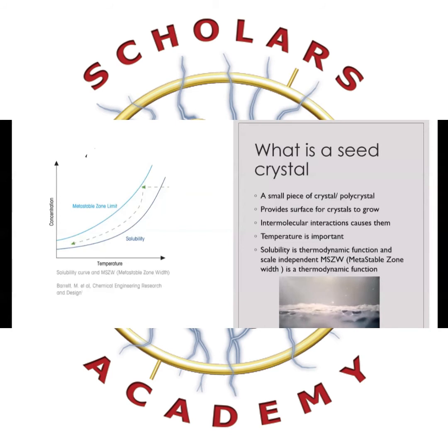Now, if you take a look here on the left-hand side, I have a solubility curve and an MSZW, metastable zone width, which I'm going to explain. Having decided that a process should be seeded, the next step is to identify at what temperature or what point the seed should be added. This is where the solubility or the MSZW metastable zone width data can be a significant benefit. A rule would be to add the seed particles midway between the solubility curve and the metastable zone.